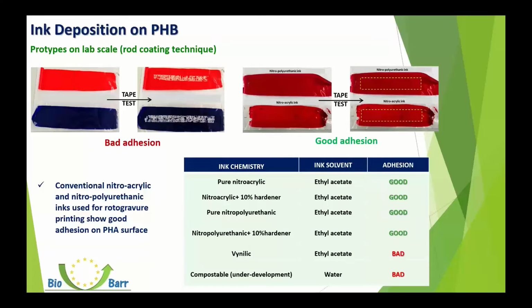As final functionalization, we investigated the ink deposition on PHB. The ink deposition is very important in flexible packaging, as it is used to make a packaging recognizable on the market, but also to give to the customer some information about the food products. We decided to investigate the use of conventional inks used both in rotogravure printing and also in flexo printing with different chemical natures. For example, we investigated nitroacrylic and nitropolyurethanic inks that are usually used for printing polypropylene, and also a vinylic ink that is commonly used to print polyester.